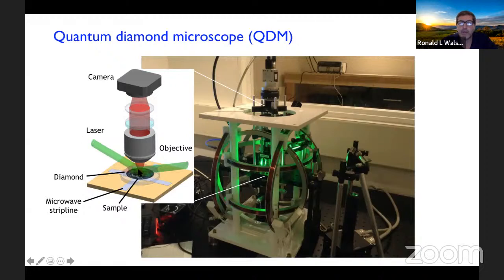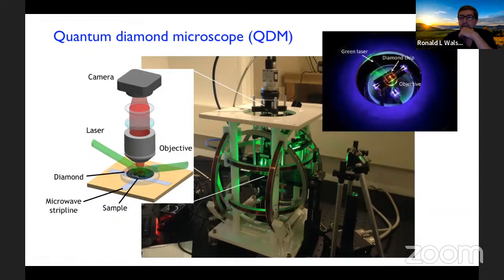Note how I'm showing it here. It comes in often in what's called a total internal reflection mode at an angle. So the NVs are illuminated by the green light, but typically the green light does not pass significantly into the sample. This means the green light is not affecting the sample. And then the NVs will fluoresce, and the fluorescence will be collected with optics onto a camera, so we can take images of the NV fluorescence in different parts of the diamond and hence learn about different parts of the sample. This shows you a photograph now looking down.